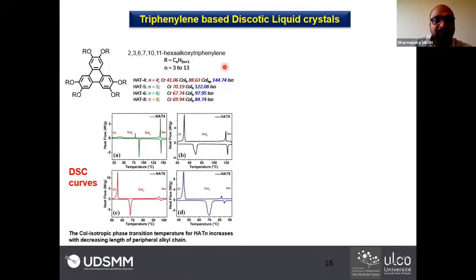Triphenylene-based systems. First we discovered this triphenylene-based system. You can see here the triphenylene molecule, and depending on the length of the alkyl chain, there are various homologous members of this series. Basically, from HAT4 to 8, these are the 4 members in the discotic family. These are the DSC curves. DSC is differential scanning calorimetry, which is really important to know what the phase is and where the phase transition occurs. As you can see here, HAT5, 6, and 8 show a hexagonal columnar phase in between the crystalline and isotropic phases. But HAT4 shows 2 phases between the crystalline solid and isotropic: the hexagonal plastic phase and the hexagonal columnar phase.